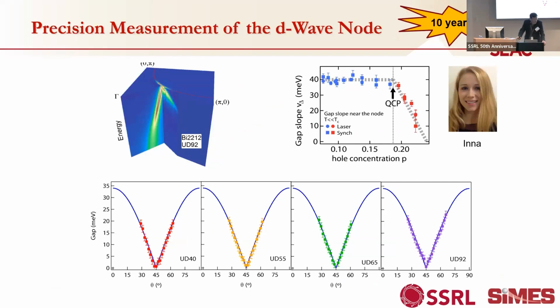And another 10 years passed, and that's the experiment. That's the thesis work of Inna Vishik. As you can see, for an anisotropic D-wave superconductor, the most sensitive parameter is the node of the D-wave, where the gap goes to zero, and how it goes to zero. It turns out that she finds that for these 4 samples, even though the superconducting transition temperature changes dramatically from 40 Kelvin to 90 Kelvin, the node doesn't change at all. The 4 data sets show the slope is the same. However, at a critical doping, you suddenly see changes. So that's a very important progress.